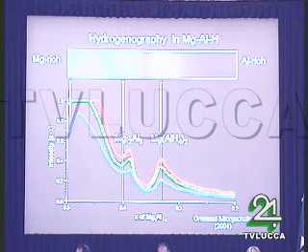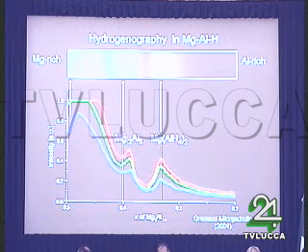What we can certainly say is that our films, which are evaporated, we just sputter magnesium and aluminum metal. We cover a little bit with palladium, that these films have a clear enhanced reactivity with hydrogen at a composition which would correspond to the magnesium alanate.